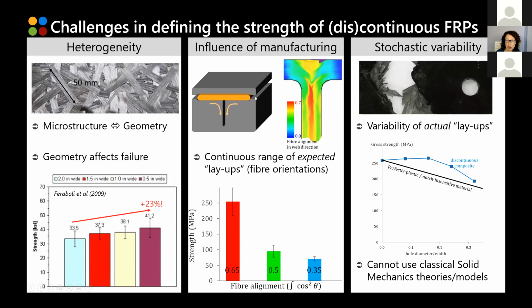So, for instance, if you try to manufacture a T-joint as the one that you can see here, you can see from process simulations that we basically have different alignments of the fibers at different points, and therefore we are going to have necessarily different mechanical properties at different points. And the thing that I think is key for this type of materials is that you have a continuous range of different fiber properties due to the different fiber alignments just in this very small area of a specimen.